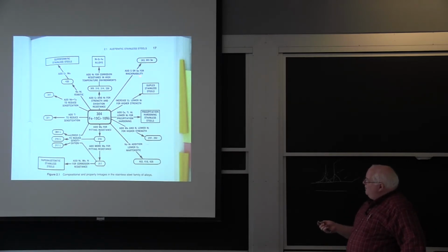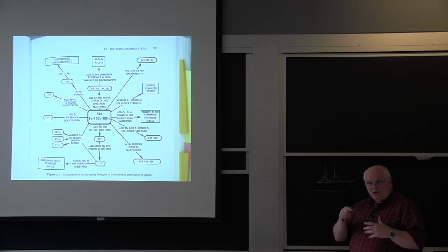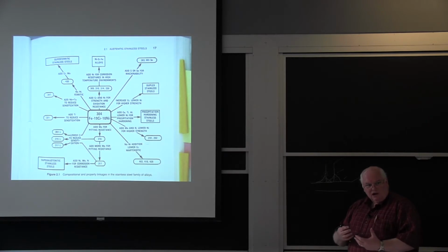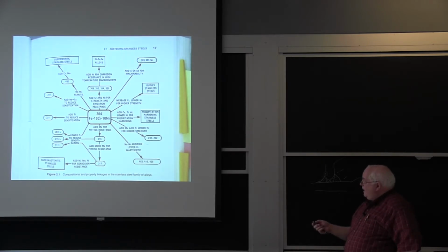Anyway, so it makes it non-weldable because the sulfur forms an iron sulfide. Remember I told you had to have the right manganese to sulfur ratio to tie up the iron sulfides, or otherwise you end up with a liquid phase iron sulfide at the interface, and that cracks when the material is shrinking. So it's there for machinability.